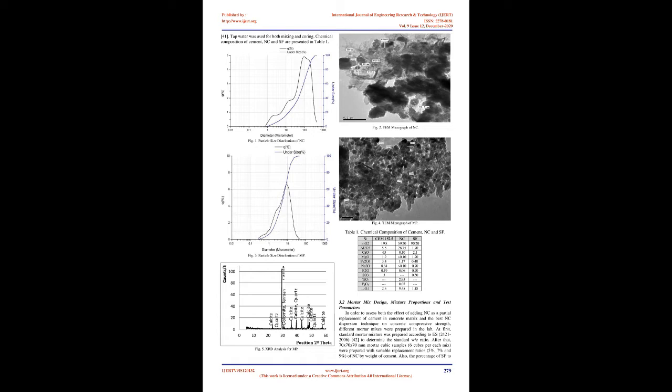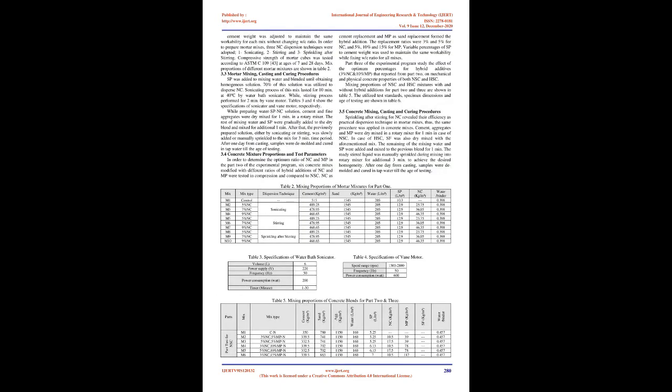Aliabdo et al. 14 reported that reusing MP as sand replacement was more effective in enhancing mechanical properties of concrete compared to using it as cement replacement. In addition, both replacements of marble produced less porous concrete compared to conventional concrete. Using 10% of MP as a partial replacement of either cement or sand by weight revealed the best improvements in that study.